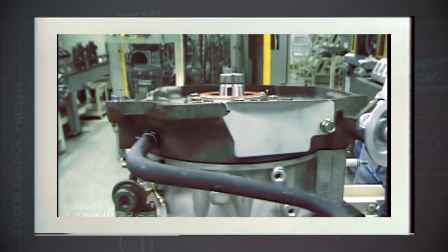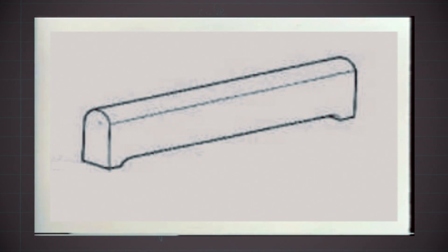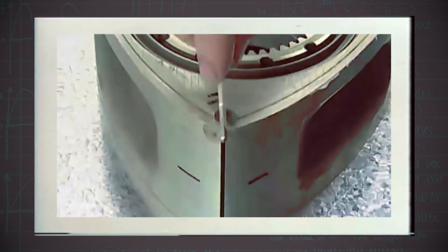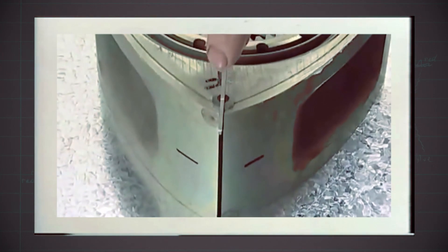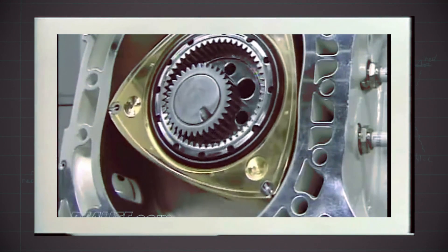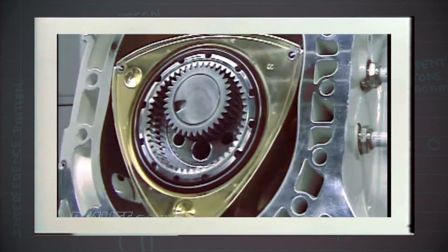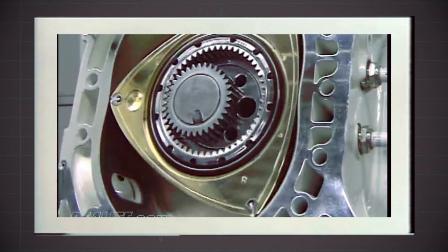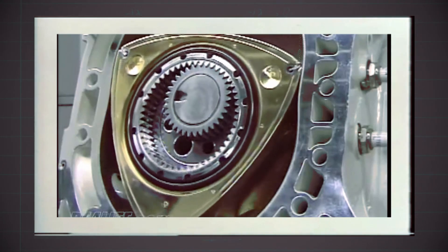From 1967 to 1973, Mazda employed the use of a 6mm or .24 inch thick aluminum impregnated carbon apex seals, which were developed from a joint venture between Mazda and Nihon Carbon, utilizing Nihon's pyrographite high strength carbon compound. To an extent, this carbon version was self-lubricating, which offered relief in the issue facing the rotor housing wall surface. Additionally, these seals were used in conjunction with an aluminum rotor housing, in which the walls were chrome plated.